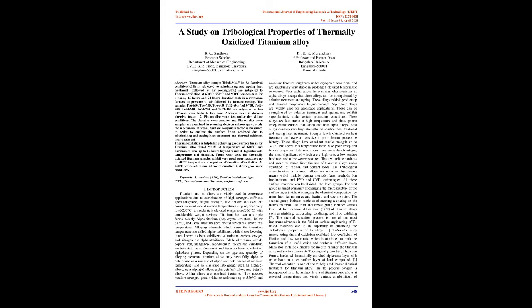Titanium has 2 allotropic forms, namely alpha titanium, HCP crystal structure, below 882 degrees Celsius, and beta titanium, BCC crystal structure, above this temperature. Alloying elements which raise the transition temperature are called alpha stabilizers, while those lowering it are known as beta stabilizers. Aluminum, carbon, oxygen, and nitrogen are alpha stabilizers, while chromium, cobalt, copper, iron, manganese, molybdenum, nickel, and vanadium are beta stabilizers. Zirconium and hafnium have no effect on alpha/beta phases.